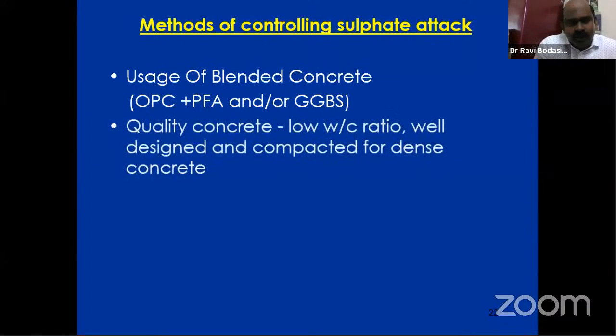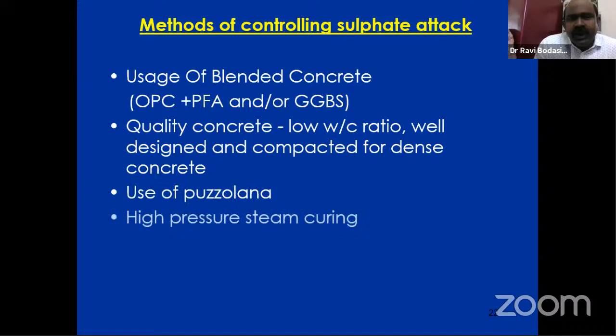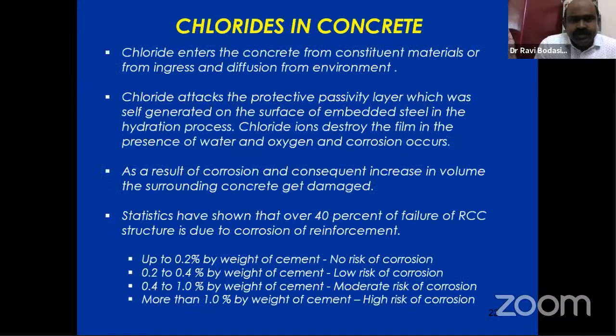Quality of concrete: low water cement ratio, well designed and compacted for dense concrete. Once the concrete is properly compacted, all the entrapped air will come out, and you will have a dense, solidified concrete, so that it won't allow any water to percolate through the element. Also use of pozzolana and high pressure steam curing.